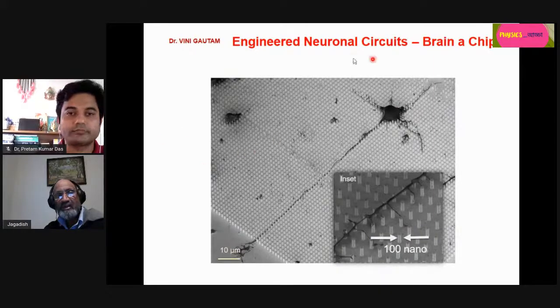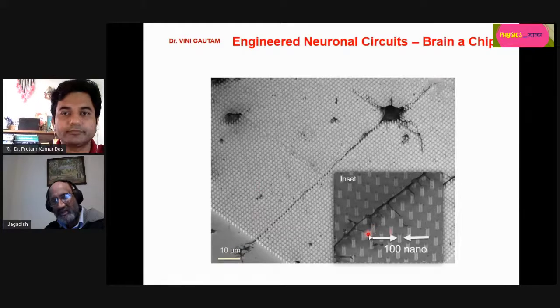So here's the case. This is the work of my young colleague, Dr. Vinny Gautam, where she tries to grow the rat neuronal cell and the cell body on indium phosphide nanowires. These are all indium phosphide nanowires. You can see these nanowires here, about 100 nanometers in diameter or so. You can see these axons or dendrites really follow these nanowire patterns beautifully, and they show very interesting properties, and that's what we're exploring at this stage.